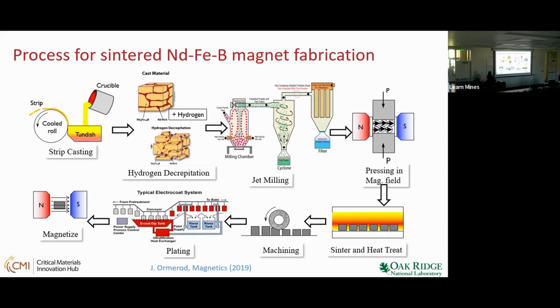Then once you do the machining, again, you are cutting into ring magnets, small sizes and shapes and all those things. Then the plating, we saw already, John talked about. So nickel, copper, nickel is the standard thing. You have to coat it with nickel or copper, or nickel, copper, nickel. The coating is to prevent oxidation, otherwise the rare earth iron will oxidize.